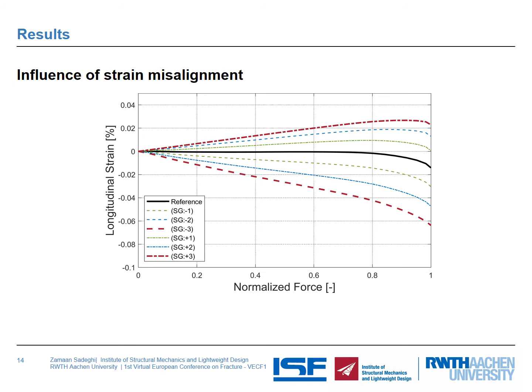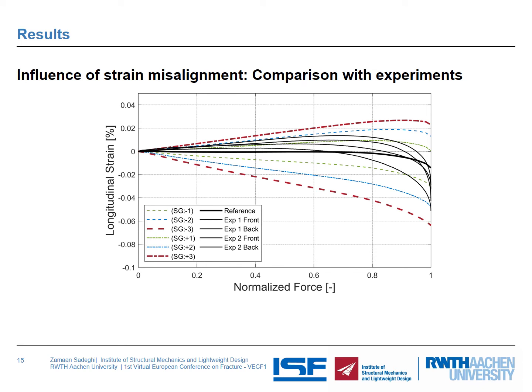As you can see here, the strain variation for different strain misalignments is shown, from 1 millimeter to 3 millimeter from both sides, from the right side of the zero-point strain and also from the left side of the zero-point strain, with the help of the FE analysis. And it's compared with the reference model, which is the FE model. Here in this slide, you can see that even a very small strain misalignment can lead to very big changes in the strain which is recorded in the strain gauges. So if we compare the experimental results, you see that they simply lie in the upper and lower band of the analysis that we implemented here, up to 3 millimeter misalignment in the strain gauge installation.